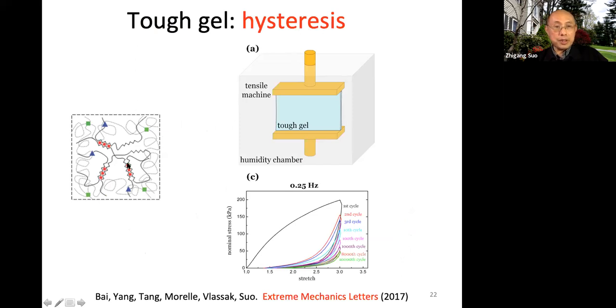with a tremendous hysteresis, right? With this unzipping. First of all, this material, this we knew for a long time, has enormous hysteresis if you just test it without a crack. Enormous hysteresis in the first cycle. After the first cycle, you unzip a lot of ionic bonds. The second and later cycles have a tiny hysteresis, but it still keeps damaging, even after this many cycles, 10,000 cycles, something like that. Yeah, you keep damaging. It's not a great material if you're an engineer, right?